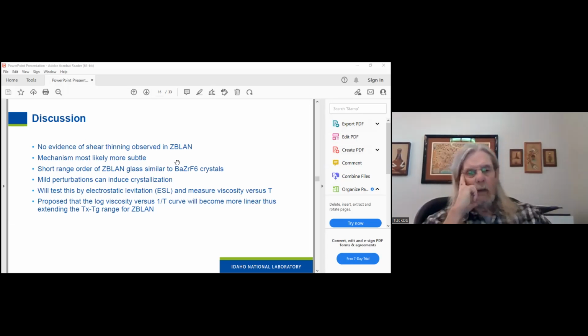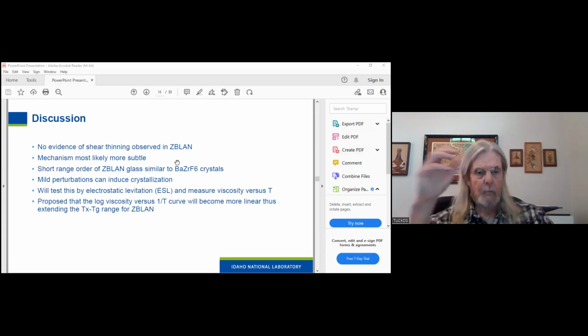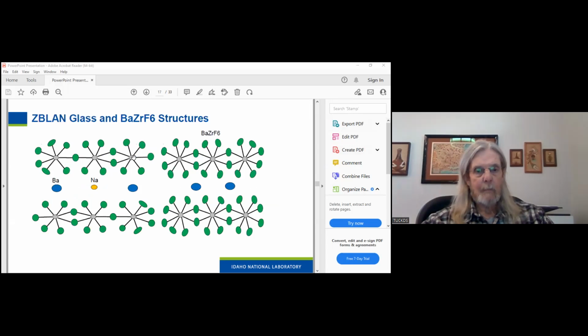Typically, T sub X minus T sub G for ZBLAN is about 90 degrees centigrade, whereas for fused silica, it's several hundred degrees C. So that's the reason you do not see crystallization in silica, and you do in ZBLAN. It's very difficult to draw fiber within that range unless you have extreme temperature control.